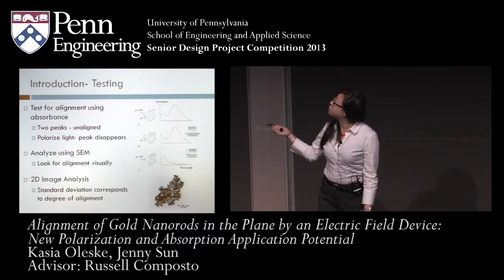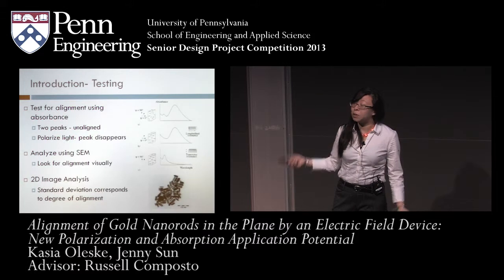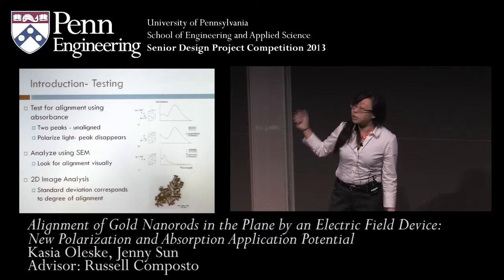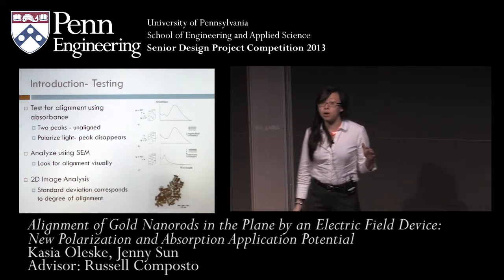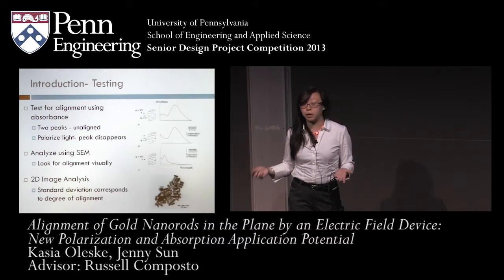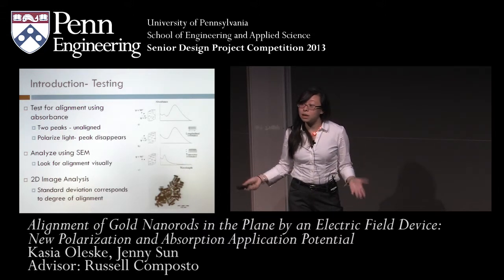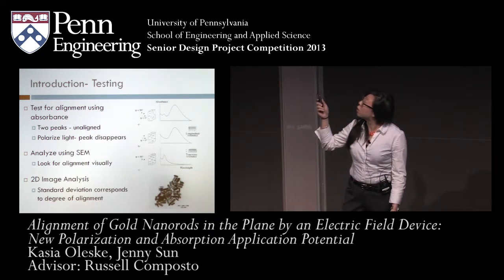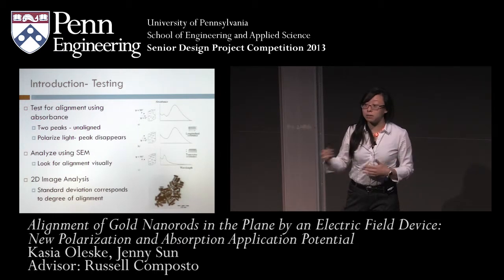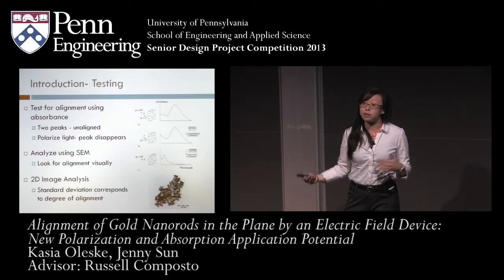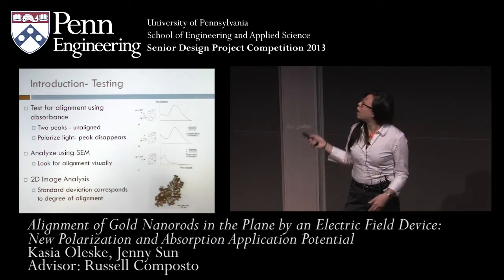And so the way we would test for alignment, there's a couple ways. First way is using absorbance. So nanorods, when they're randomly oriented, have two absorbance peaks, which means they absorb two different wavelengths based on their size. And so if we actually manage to align them in the plane, if we polarize incoming light, we should be able to see the disappearance of one or the other of these peaks due to resonance.